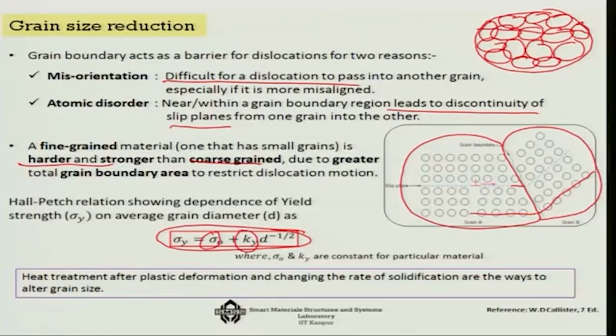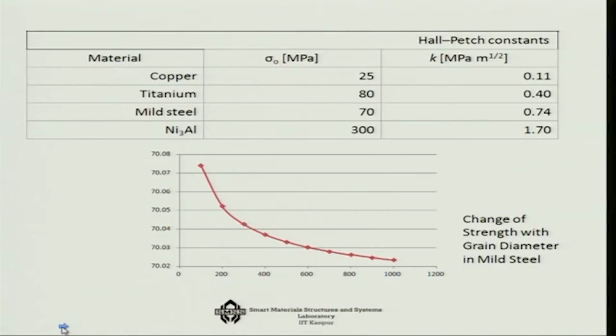Okay. Interestingly, that is the same thing Petch has later on seen, that is not only for mild steel, but for other materials also this same thing happens, and people have found out through experiments the values of these Hall-Petch constants, like for copper sigma 0 is 25 MPa, and the K is about 0.11 MPa meter to the power half, for titanium it is 80, 0.40, mild steel it is 70, 0.74, Ni3Al it is 300 and 1.7.